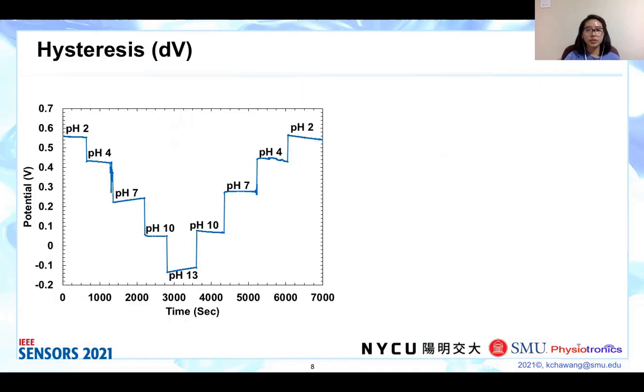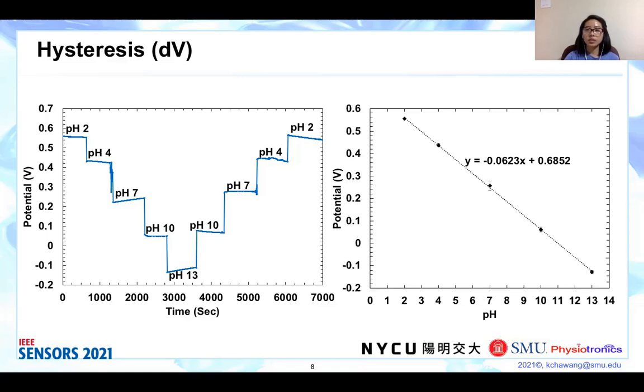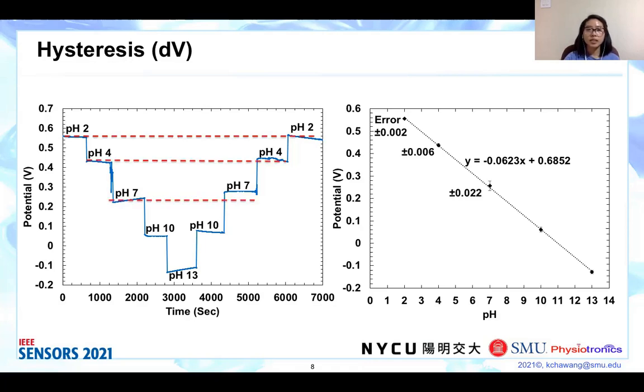The plot here shows the test sequence from pH 2, 4, 7, 10, 13, 10, 7, 4 to pH 2, and this is done to find the hysteresis. The sensitivity slope still shows a super-Nernstian sensitivity of 62 millivolt per pH. Hysteresis at pH 2 is 2 millivolt, at pH 4 is 6 millivolt, at pH 7 is 22 millivolt, at pH 10 is 10 millivolt, and at pH 13 is 7 millivolt.